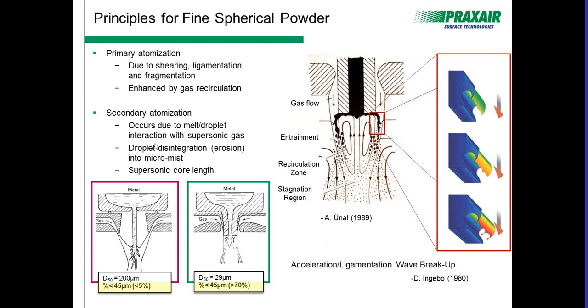And what's happening there is the liquid droplet is now interacting with supersonic gas. And you can engineer these structures to operate at Mach 1, Mach 2, even in some cases Mach 3. And that velocity mismatch between the gas and the liquid really results in this microerosion. And so these larger droplets are being eroded as they're driven downstream. And this erosion product, or this micromist, is the finest droplets.